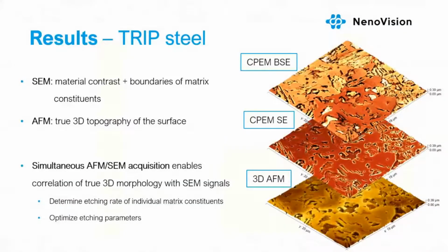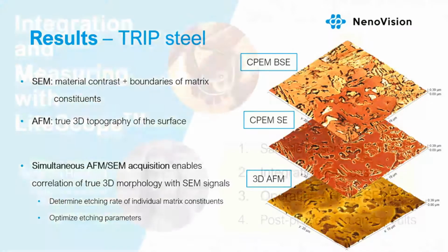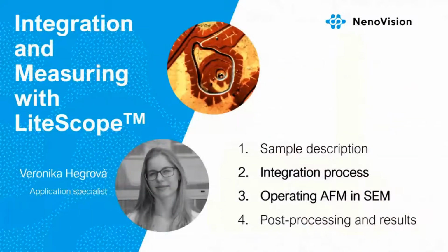Let's have a look at the processed and saved images of the TRIP steel. It's nicely visible how important the simultaneous measurement is. We are able to distinguish different phases and its boundaries thanks to SEM signals, but we need AFM to determine which phase is etched more and which less. It enables us to optimize the etching process to obtain the smoothest surface possible. Now, I would like to quickly repeat the integration and measuring procedure on a different brand microscope.